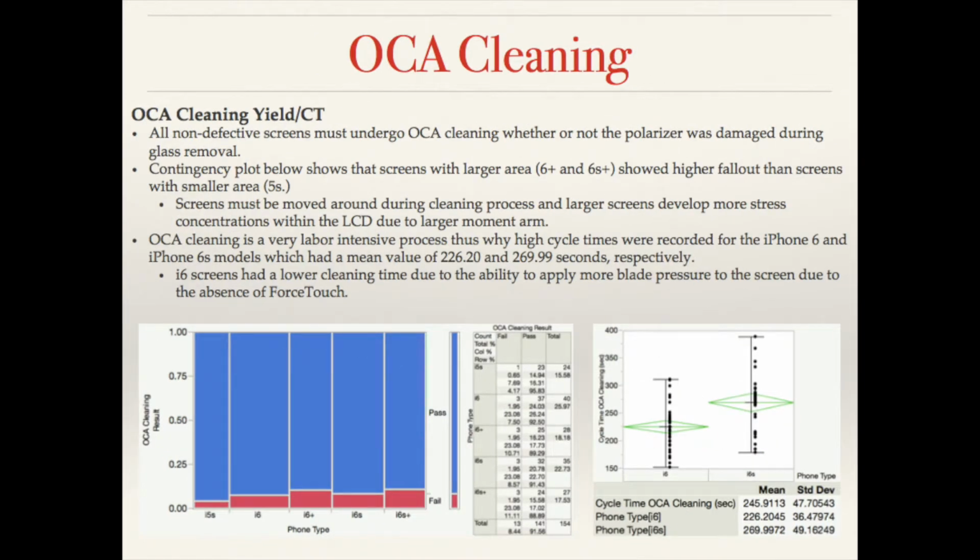As there is a layer of OCA above and also below the polarizer, it was found that all non-defective screens must undergo OCA cleaning whether or not the polarizer is damaged during glass removal. A higher fallout rate was seen for LCDs with a greater surface area as they required more time and effort to clean. However, the overall yield rate of the process was found to be 91.56% with a very high cycle time of around 245 seconds.